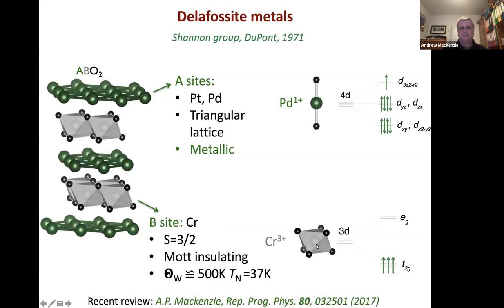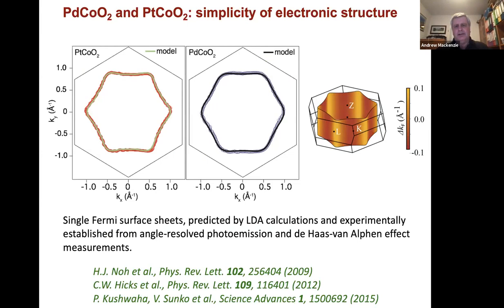So one of the reasons perhaps that the DuPont group didn't follow up on their discovery of these metals, at least in tremendous detail, was that back in the 1970s, you really didn't have many of the techniques that we use on them regularly now, and which I think are necessary to really appreciate how much potential the materials hold. So as we'll see in more detail later, it's possible to do rather beautiful photoemission experiments on these materials. And that combination of photoemission and de Haas-van Alphen measurements allows us to know that either platinum cobaltate or palladium cobaltate have a remarkable and beautiful simplicity. You just have one half-filled band crossing the Fermi level, forming a Fermi surface, which is highly faceted and looks a pretty good approximation to a hexagon.